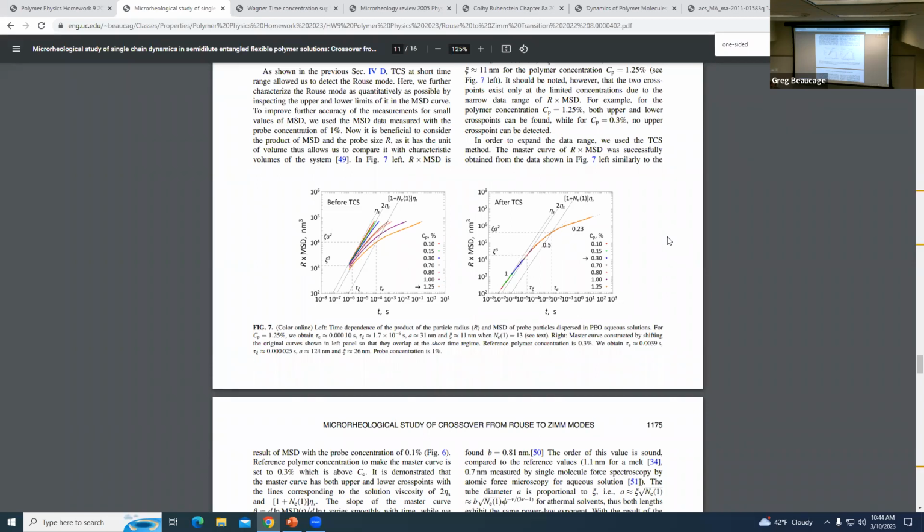So if you're looking across particle sizes, if you want them to be on the same curve, you have to multiply the mean squared displacement by the particle size. Then you'll get kT divided by viscosity times 6 pi, and that's it. So you don't have to worry about particle size then. That makes it more useful, right? So that's why this oddball thing shows up here, because the particle size isn't important in the end to the analysis.